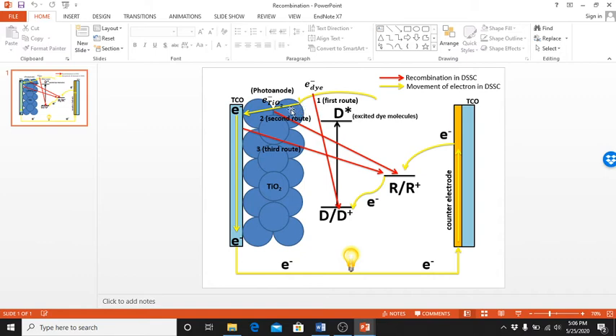The second route is the electron successfully travels to the TiO2. But in the meantime, because the TiO2 nanocrystalline is a very thick layer, the electron in the TiO2 will recombine with the redox electrolyte. When that happens, the number of electron-hole pairs will be reduced, and this reduces the overall generation of photocurrent and voltage. And last but not least is the recombination between the electron of the transparent conductive oxide, our substrate, and the redox electrolyte. This is also a possible route for the recombination to occur.